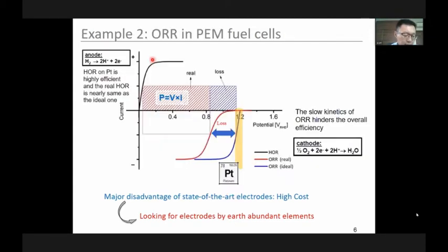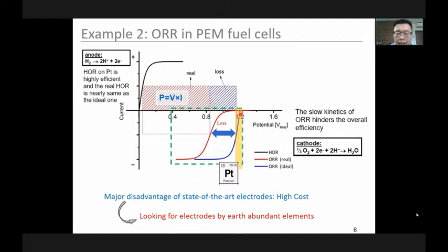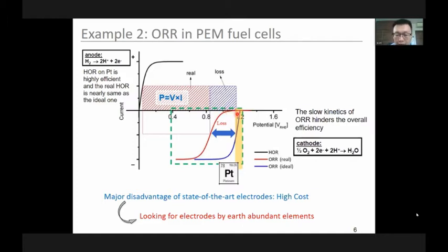The second example is the ORR in proton exchange membrane fuel cells. This famous diagram tells us why a PEM fuel cell cannot give 100% energy conversion efficiency. The main problem is energy loss at the cathode ORR site. The blue curve represents ideal ORR at the thermodynamic equilibrium of 1.23 V — above 1.23 V is OER, below is ORR in principle. But on platinum, the best catalyst in the periodic table, the real ORR happens at the red curve, which is left-shifted compared to the ideal. This voltage shift reflects power loss. This loss cannot be avoided because in this potential range, platinum surface is blocked by oxygen species like OH, and until you apply a sufficiently negative ORR potential, metallic platinum is exposed and ORR can happen.